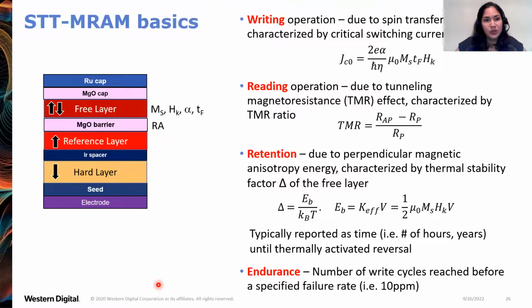So let me review these critical performance parameters of the STT-MRAM. So we talked about the writing. This happens by spin transfer torque, and it's characterized by a critical switching current density, JC0. And I want to point out that the switching current density is largely dependent upon the magnetic properties of the free layer material: saturation magnetization, anisotropy field, damping parameter, and free layer thickness. The reading, this is done by the TMR ratio, also very highly materials dependent. This is why we work with the cobalt iron MgO materials system for high TMR.